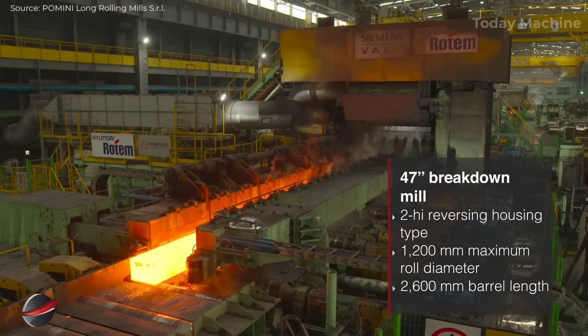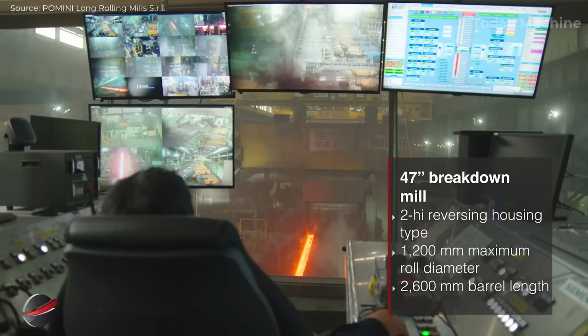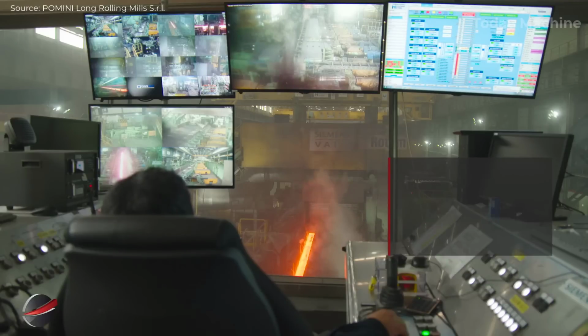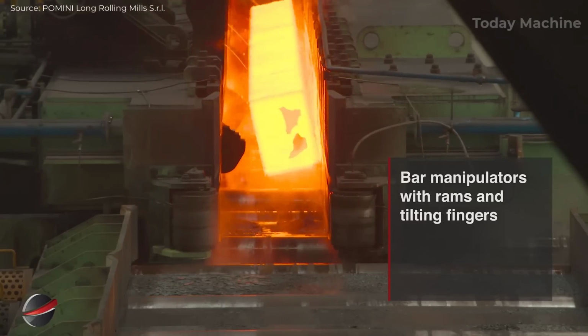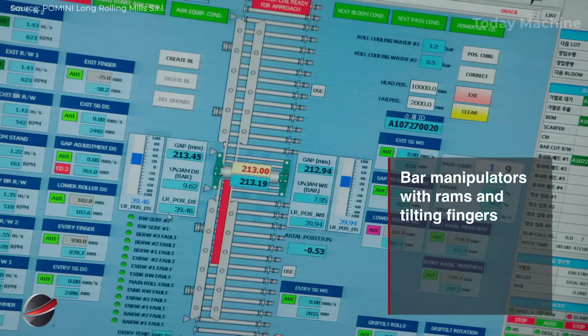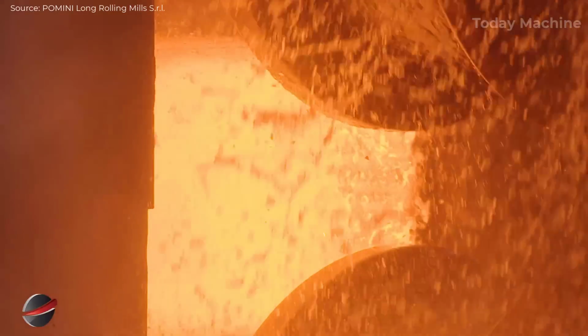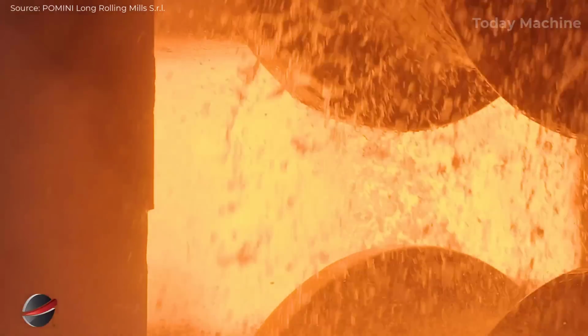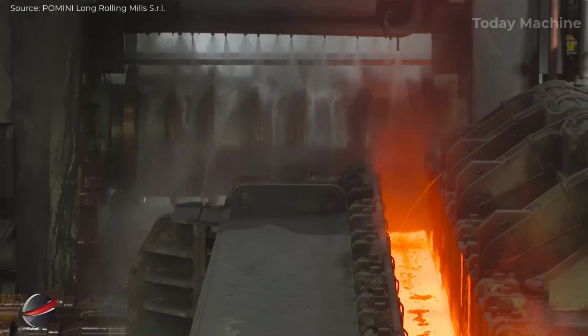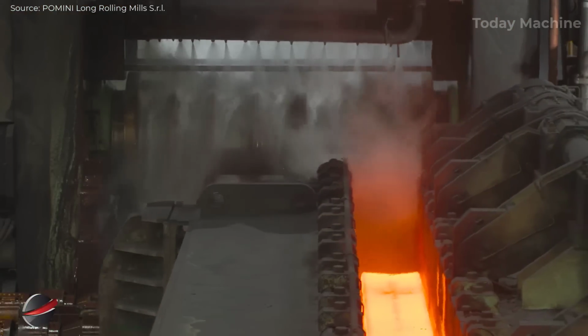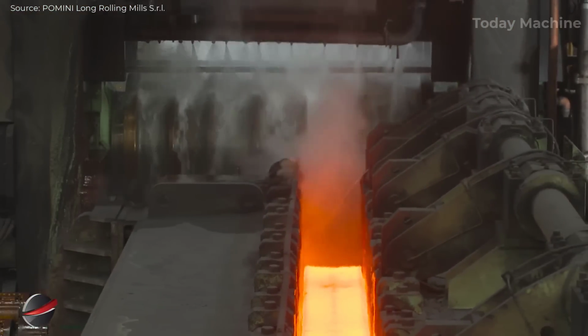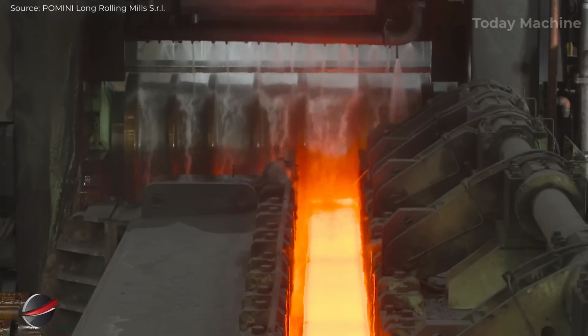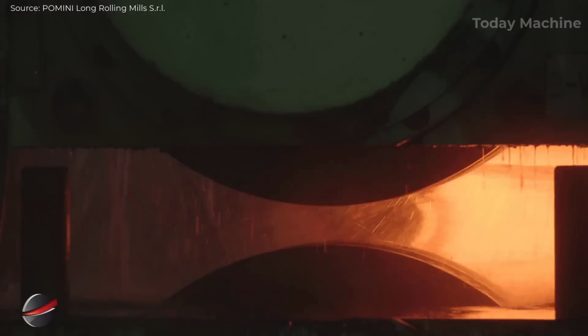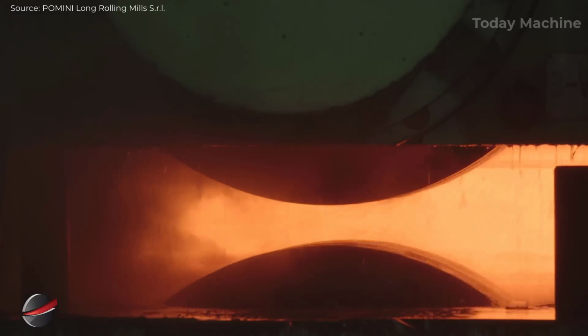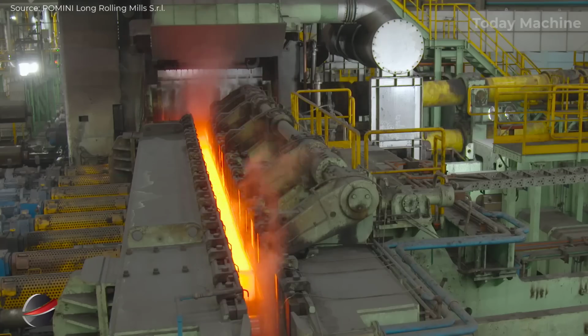After descaling, the heated blooms enter the breakdown mill, which consists of a two-high reversing housing type mill with a maximum roll diameter of 1,200 millimeters and a barrel length of 2,600 millimeters. The mill handles both hot and cold charging and processes large blooms of 390 by 530 millimeters in size and 3.5 to 8 meters in length.